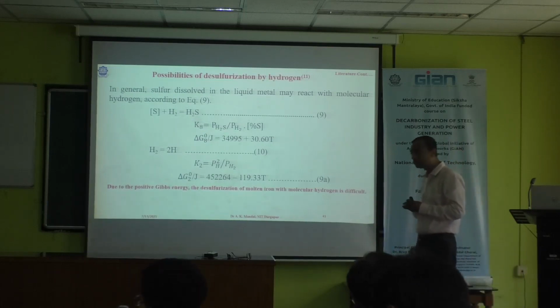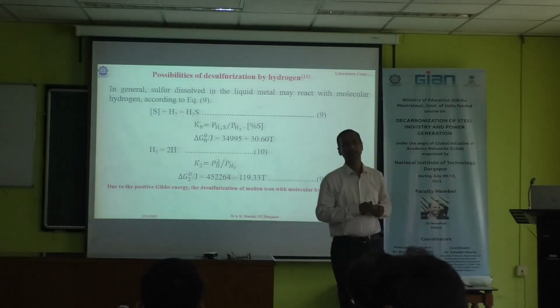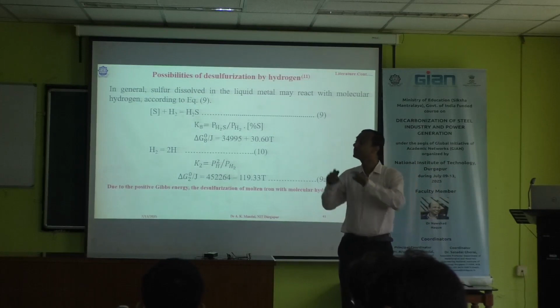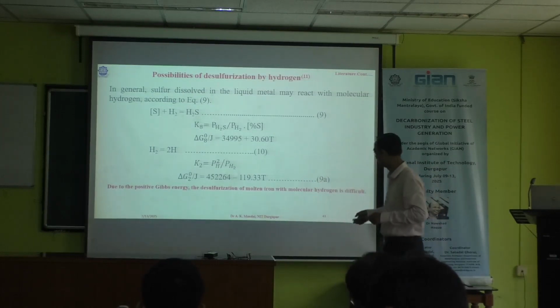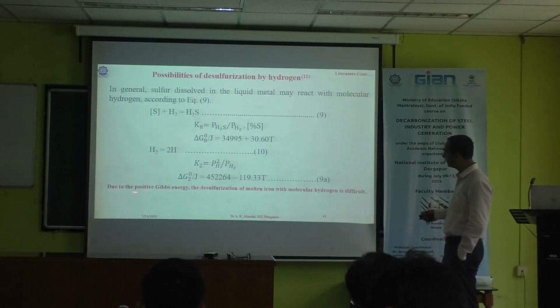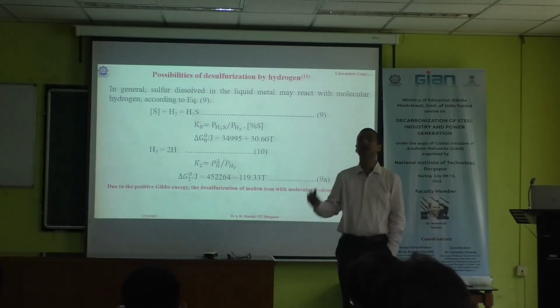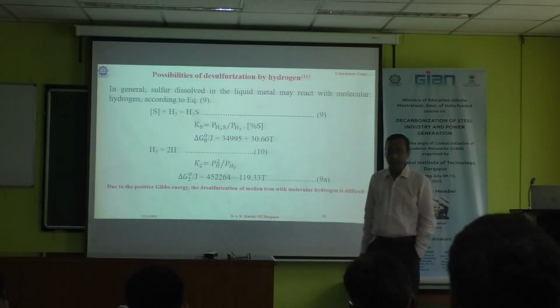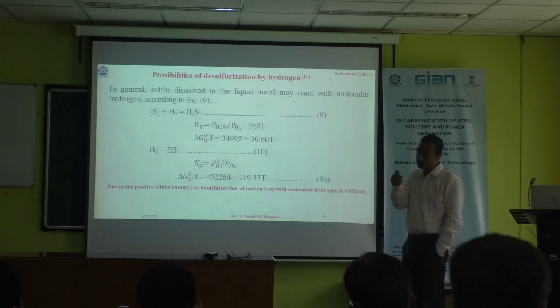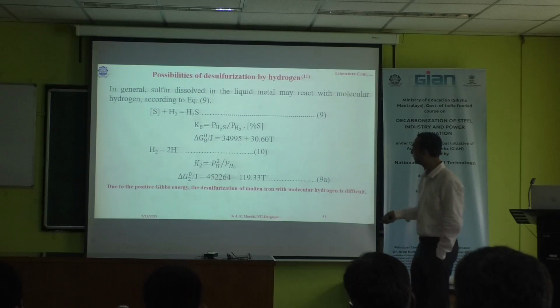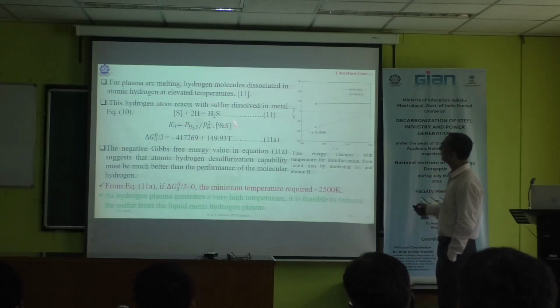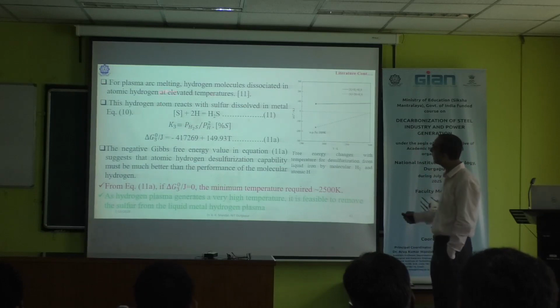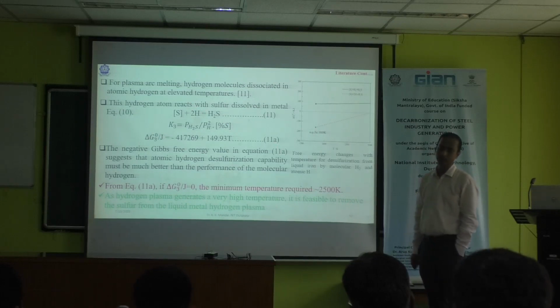Hydrogen can react. But the problem is the reaction of hydrogen with the sulfur which is present in the liquid metals. If you see the reaction, the positive Gibbs free energy restricts the sulfur from reacting with hydrogen gas. So to react with the sulfur present inside the liquid, it requires an ionized phase. When it is in the ionized phase, hydrogen plasma generates a very high temperature, which is effective to remove the sulfur from the liquid. Then it is possible to reduce.